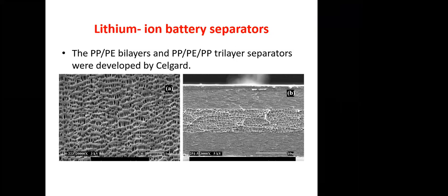To safeguard the battery, you may be aware that in 2016 the Samsung Note 7 blasted because of a separator issue. So now people are applying a ceramic coating on the separator to increase the thermal stability, so that it can operate at higher temperature also, and it can be charged fast.